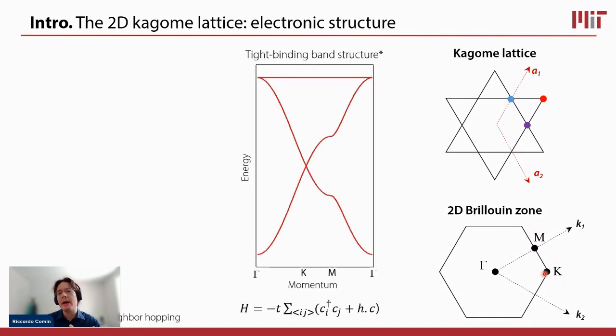And so if we now look at the band structure, so if we look at the electronic bands that exist in the Kagome lattice, and by electronic bands, I simply mean the set of energy levels for electrons as a function of momentum, we can look along these 3 high symmetry directions. So going from gamma to the corner of the Brillouin zone, so from the center to the corner, and then we crawl along the edge to the M point, and then we go back to the gamma point. And if we move along this particular path in reciprocal space, then we see that the electronic bands have this particular shape that you see in this drawing here.